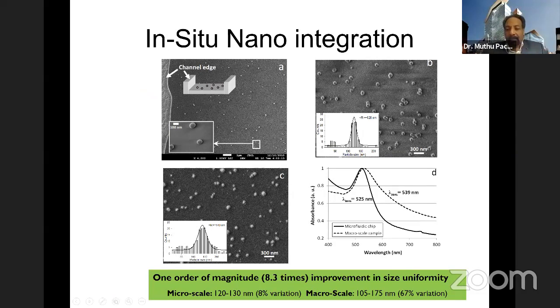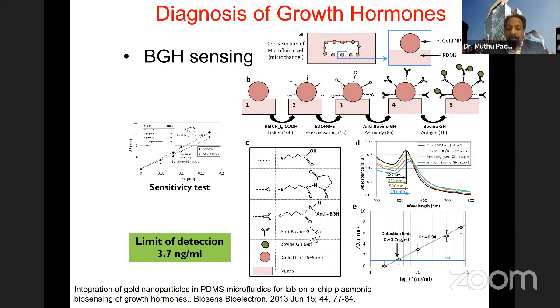These in situ synthesized particles also have a very good uniformity in size compared to what you make outside in typical tubes. So you can see the inside of the microfluidic channels. You follow the same bioprotocols, and after you immobilize and build nanoparticles by in situ synthesis, then you do all the bioprotocols, make the antigen-antibody interactions, and what you basically do is monitor the plasmonic shift of the localized surface plasmon resonance. Depending upon the concentration of the growth hormone, the plasmonic shift will be different. So we can go up to the detection limit of 3.7 nanogram per ml in this case, which is outstanding so far.